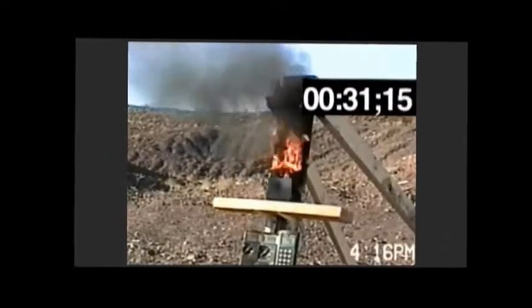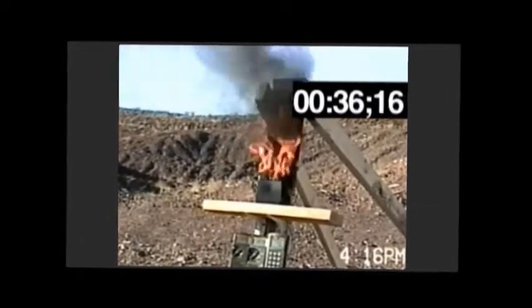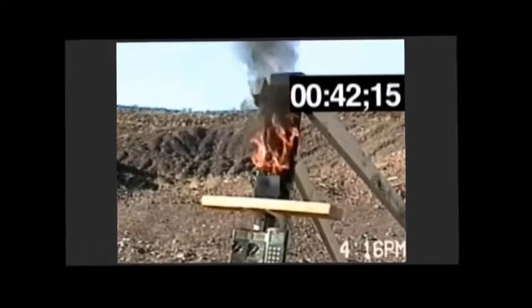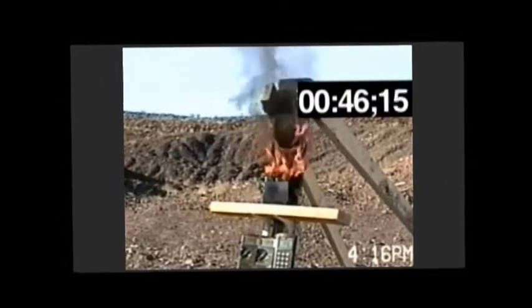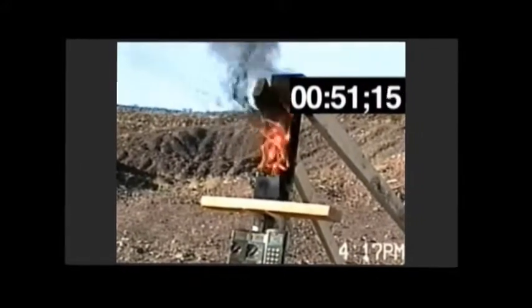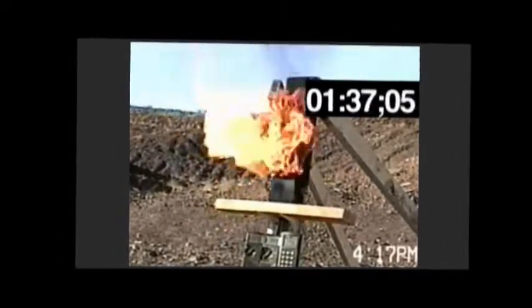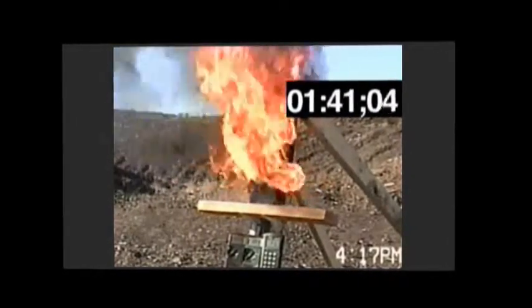As the test continues, the event in the cobalt oxide battery pack appears to slow down and become manageable. But what cannot be seen is the thermal momentum created in the adjacent battery cells from the initial reaction. Despite claims to the contrary, there is no internal or external safety device that can prevent the next series of events. One after another, the remaining 23 oxide cells in the battery pack break down and demonstrate thermal runaway.